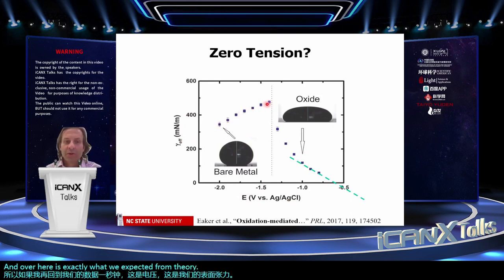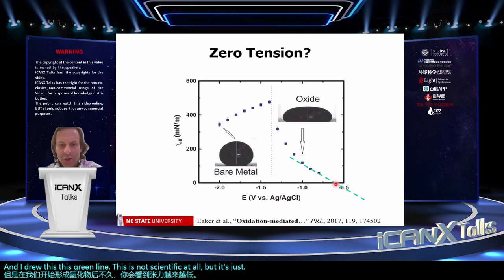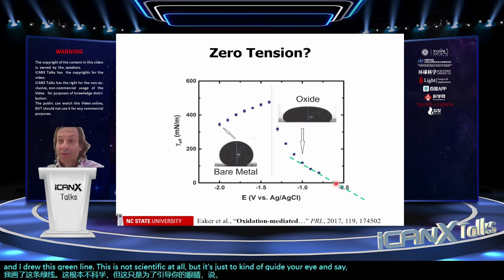This is where there's no oxide on the metal. But shortly after we start forming oxide, you see the tension gets lower and lower and lower. And I drew this green line. This is not scientific at all, but it's just to guide your eye and say, well, gosh, that looks like the surface tension might be zero.